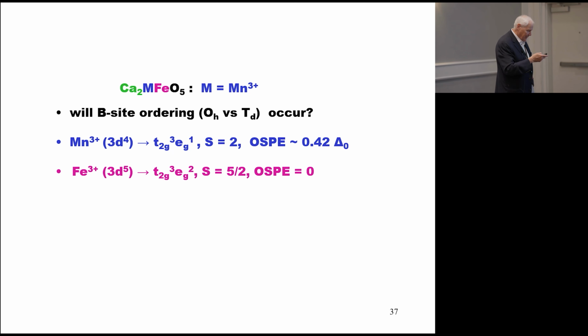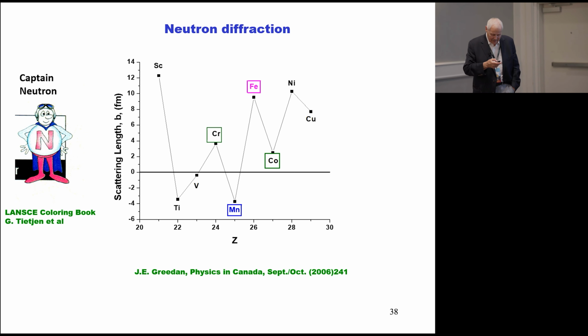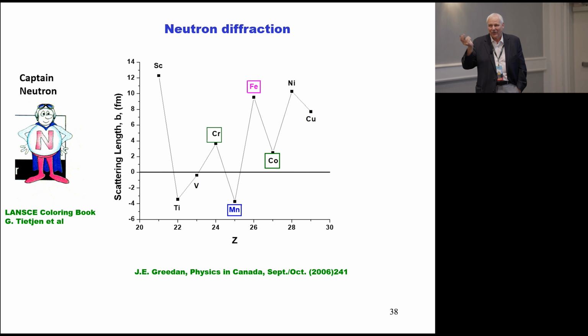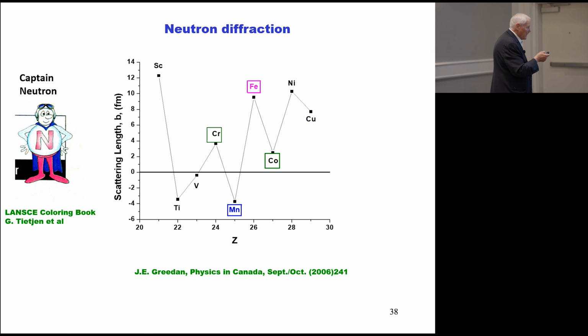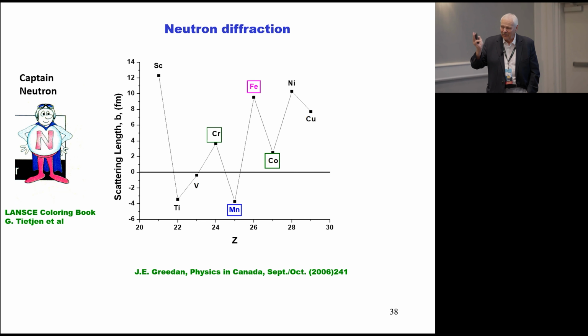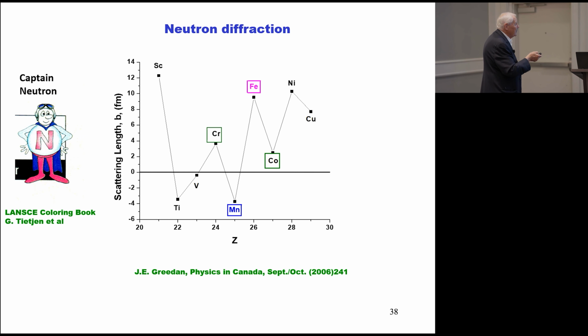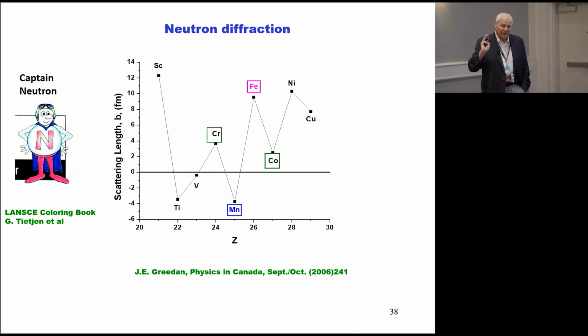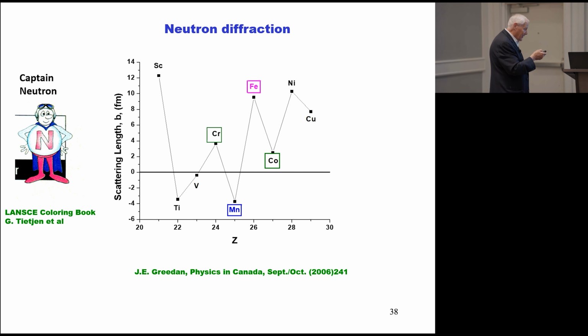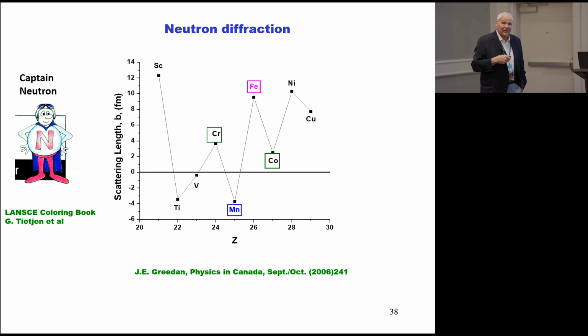Well, I'm going to propose one method, which is neutron diffraction. This is one of my favorite little superheroes, Captain Neutron. He's not as apparently fit as some other superheroes, no six-pack there, but he's an elementary particle, so we should give the guy a break. The important thing I'm going to point out here, before you're composing your hate emails, I know you can do this with X-rays, synchrotron X-rays with wavelength tuning, but I think it's really much simpler to do this with neutrons. Because if you look at the pattern of scattering lengths across the series, you can distinguish every adjacent pair of transition atoms very, very easily with neutron diffraction. And the very best case, as a matter of fact, is iron and manganese, because manganese has a very large negative scattering length and iron has a very large positive scattering length. So that's what we do.